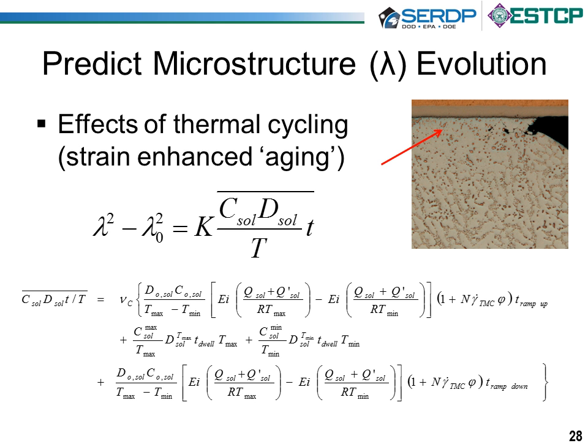And so what we have provided you with is a carefully researched and developed expression, an effective expression for the change in precipitate spacing as a function of temperature and time and cycling and everything. So it becomes this long expression, and it looks perhaps daunting, but it's all numbers. You can put in functions and expressions. You can put it in a spreadsheet. In fact, we provide a spreadsheet if you want, where you can just sit and calculate at any given time what will be the precipitate spacing as a function of time.